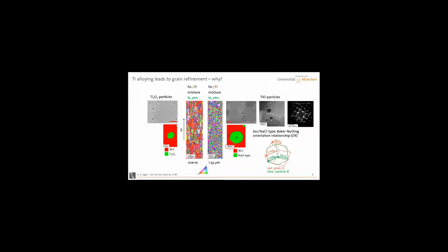That's a hexagonal crystal structure. And for the 5% titanium, we have actually rock salt crystal structure, so this is compatible with TiO. And TiO particles can form a specific orientation relationship, the Baker-Nutting orientation relationship, with a ferritic matrix. And that is one prerequisite for heterogeneous nucleation, as we've heard before today from other speakers. We could confirm this orientation relationship in the TEM, so that all fits well.